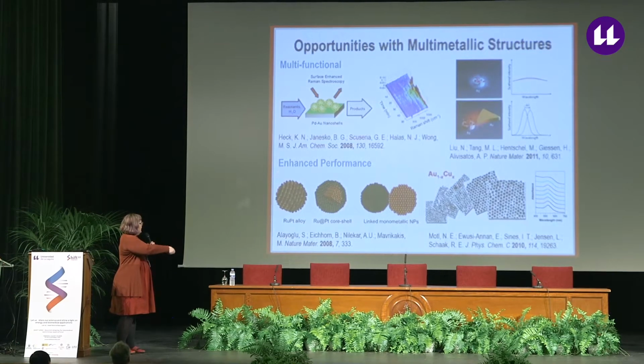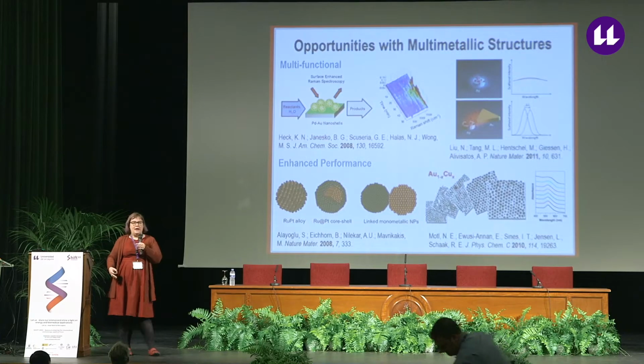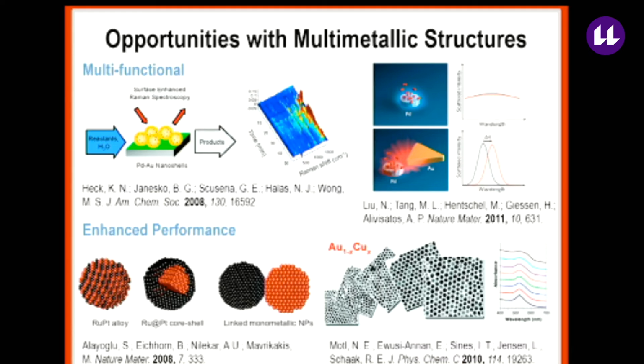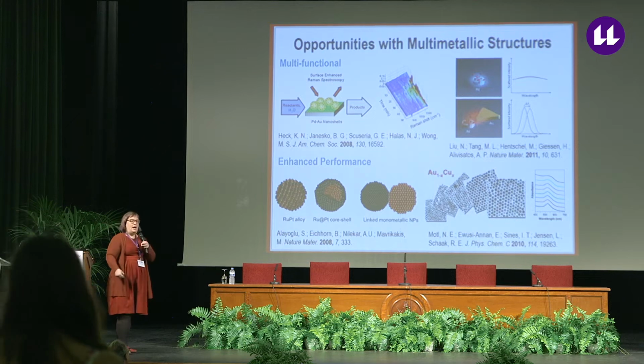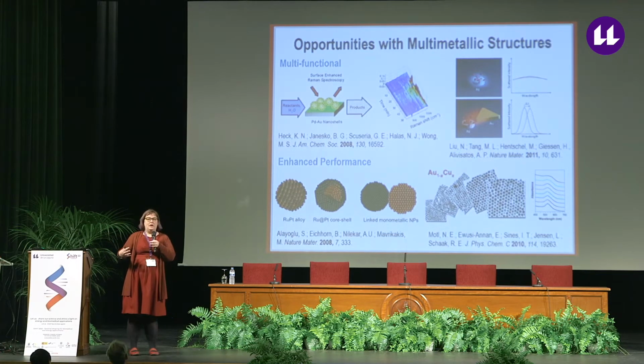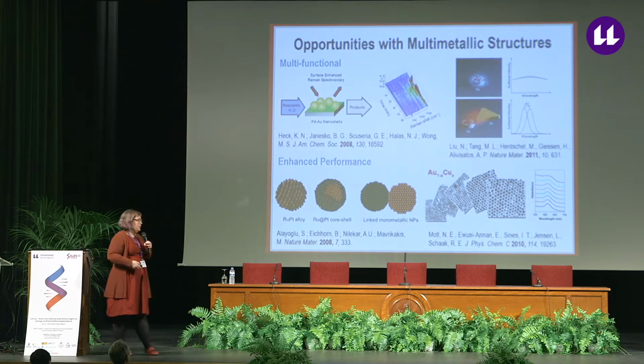And so in this specific example, they're coupling the optical properties of nanoscale gold with the catalytic or chemical properties of nanoscale palladium. But a second example, reflecting on the enhanced performance of multi-metallic nanostructures, is shown on the bottom from Manos Mavrikakis and Brian Eichhorn. And in this particular example, they were designing catalysts for the PROX reaction. And what they found was that how the two different metals were mixed at the atomic scale or at the nanoscale influenced the properties that were displayed by the catalyst, with a core-shell ruthenium-platinum nanoparticle performing the best in this particular application because of an electronic effect inherent to the bimetallic composition and that core-shell architecture.